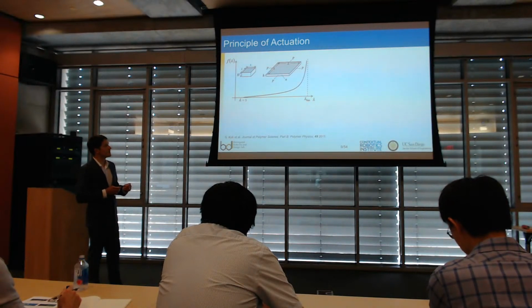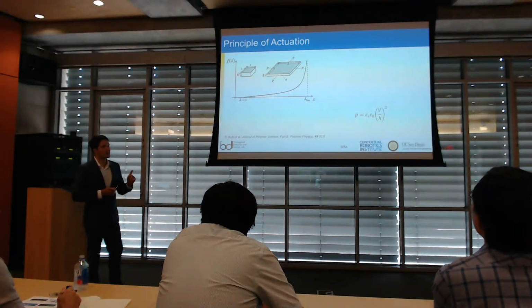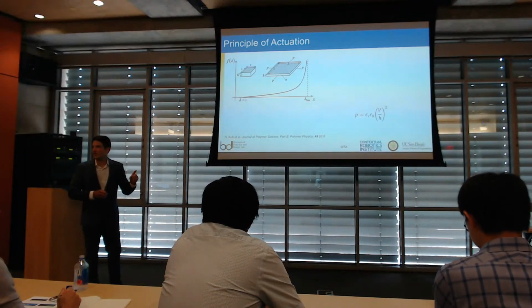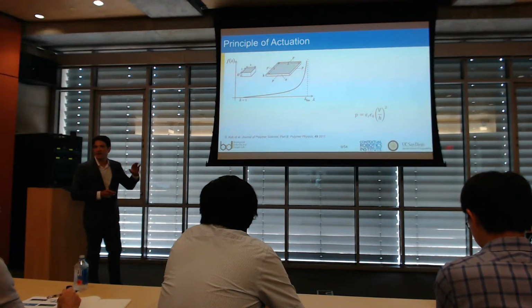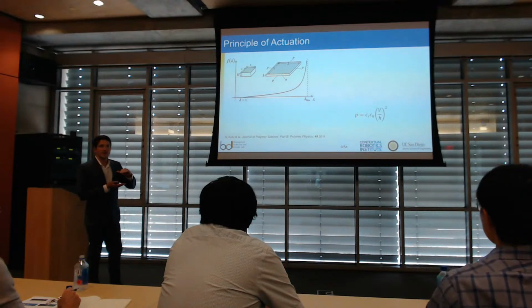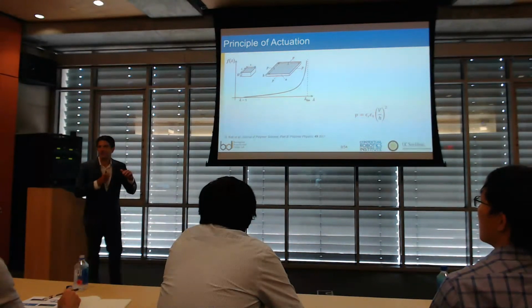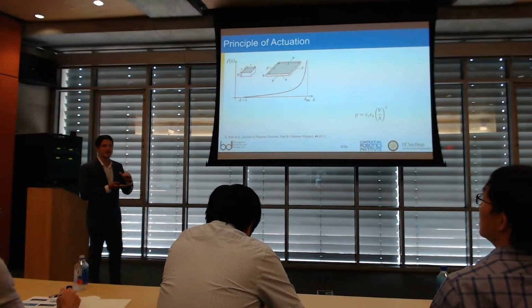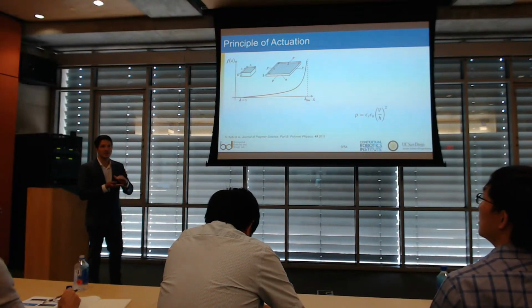For these actuators, if you'll remember, the pressure goes as the inverse of the thickness. And so what's happening is that if you apply a constant voltage, you're generating this feedback loop. So as you apply a constant voltage, you're making the actuator thinner.